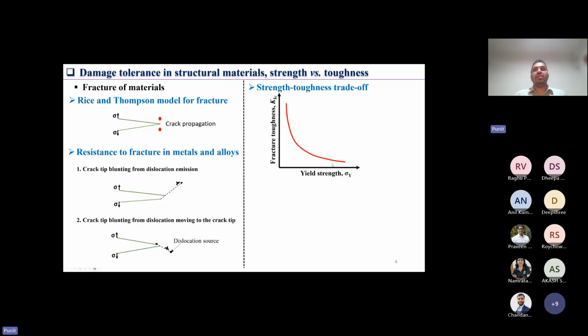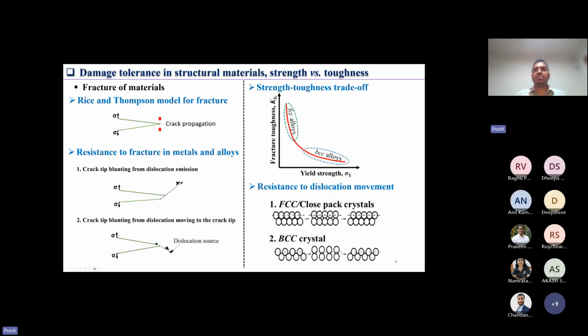For example, if you have materials with higher yield strength, it means that you will have lower dislocation activity at the crack tip, and that means you will have lower fracture toughness. At the same time, if we have materials which have lower yield strength, which means you will have more and more dislocation activity at the crack tip, those materials will have higher fracture toughness. And we can also divide these further into two broad categories. There are many exceptions to this, but if we just divide it in broad categories, we can divide into BCC alloys, because the material is not close packed, nucleation of dislocations or movement of dislocations or other defects is slightly difficult compared to FCC materials, and that's why these materials would have higher yield strength but lower fracture resistance.